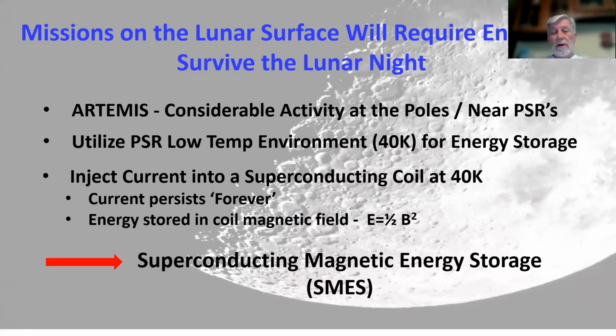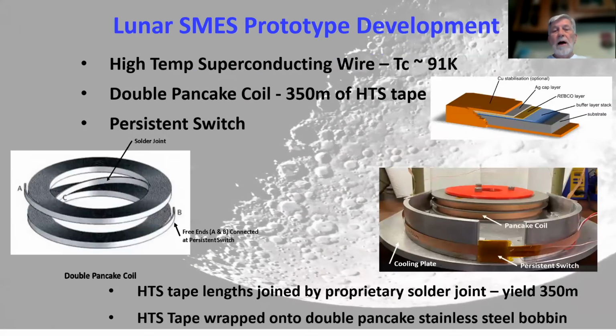The energy stored in that coil is in a magnetic field, and that energy goes like the square of the magnetic field. So we now have superconducting magnetic energy storage that can be done at 40 degrees Kelvin at the poles. We did a prototype development for this SMES. We used high temperature superconducting wire with a Tc of 91 degrees Kelvin. That wire is a multi-layer wire with about 2 microns of superconductor on top of a 100 micron or so metallic substrate for ductility and strength.